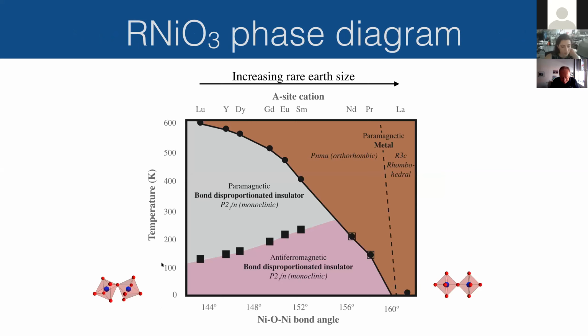So unsurprisingly, you can make a phase diagram where you have the different A-site cations. Equivalently, you can plot the nickel-oxygen-nickel bond angle. So here you have the largest cation going smaller, and the bond angle is the largest here going smaller. So you go from quite a cubic almost structure to a very distorted structure. And then if you change temperature, you get all these rich phases. So at high temperature and for just lanthanum nickelate, you have a metallic state. And as you cool down, you go into this insulating state. Almost all of the compounds do this. And finally, at lower temperature, you enter this antiferromagnetic state. So I'm going to go into a little bit more detail now on these transitions.